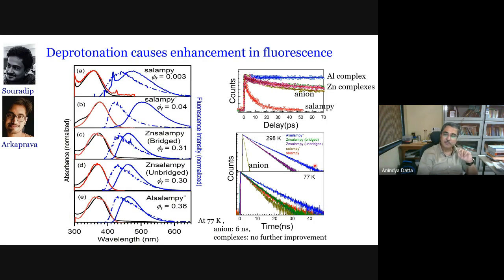But on the way, we found out that even before we make the complex, if we just deprotonate the Schiff base, Salampy, we get a significantly longer lifetime. So if we now again come back to the nanosecond time regime, this here is the fluorescence decay of the zinc complex. This is the fluorescence decay of the anion. And you cannot even see the fluorescence decay of the free base Salampy molecule here, because it practically gets over in 50 picoseconds. So the anion itself is significantly more emissive. If you look at the quantum yields, 0.003 for Salampy, 0.04, an order of magnitude increase, again for the anion, and one more order of magnitude increase upon formation of the complexes.